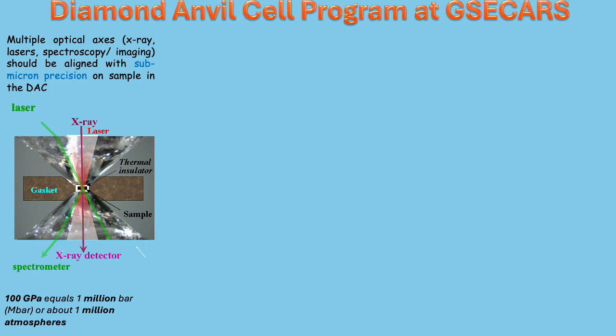The diamond anvil cell technique requires a dedicated beamline station, and the main reason for that is we have to focus X-ray on the sample inside the diamond anvil cell. But due to the high refraction index of the diamond, the visual and the real position of the sample is different, and it's very important when we want to combine multiple optical axes like X-ray, laser spectroscopy, and imaging with submicron precision that require dedicated tools developed at the beamline.